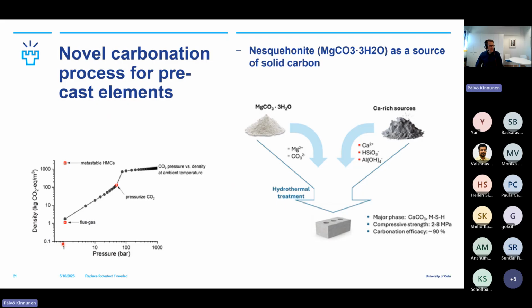And one of the major pains, let's say, in the current calcium carbonation or mineralization and utilization in construction materials, is that if you have flue gas, the density of CO2 is really low. It's something like a kilo of CO2 per cubic meter. And if you start to increase the pressure, you have pressurized CO2, which is about 100 kilos per cubic meter. But in order to pressurize the CO2, you first have to take it out of the flue gas, then you have to purify it and then compress it. And this is actually quite expensive.